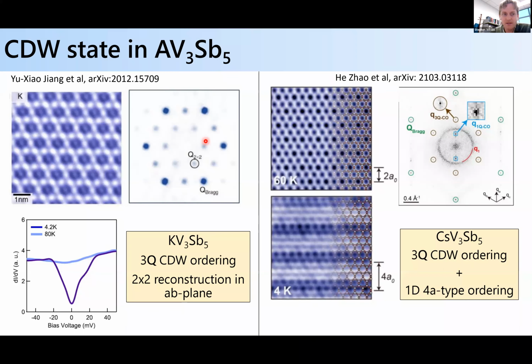Okay, but this 3Q order was also observed looking at cesium vanadium-3 antimony 5, right? So this is very beautiful data from Ilya Zeltovich's group, where again they do the Fourier transform. They can see these 2x2 peaks, which can be attributed to 3Q order due to the charge density wave instability. But then there's an additional charge texture that emerges in this cesium system as you cool down, a charge order that coexists with this 3Q order, which is a unidirectional stripe ordering, okay, which they label as 4A type ordering, where the periodicity is about 4 lattice constants. Okay. And I'll talk more about this in a moment, but first I'm going to talk about the 3Q order in this system.